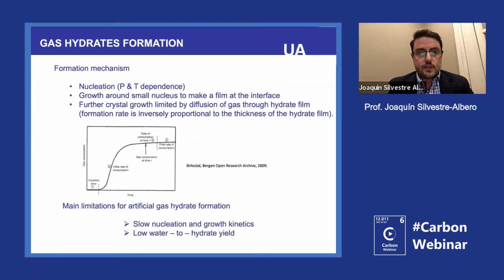When you think about the mechanism and you take a look at the literature, mainly for the bulk phase, what you see is that when people are trying to grow gas hydrates, the first thing you have to do is mix, or put in contact, water with a high pressure of methane. There is always an induction time, so you need a few minutes or a few hours until you get some nuclei. And immediately there is the growth of small crystals around this original nucleation size. But there is always a problem.